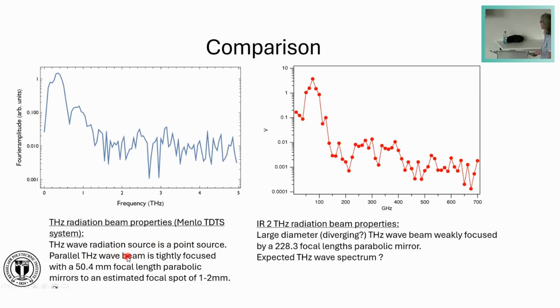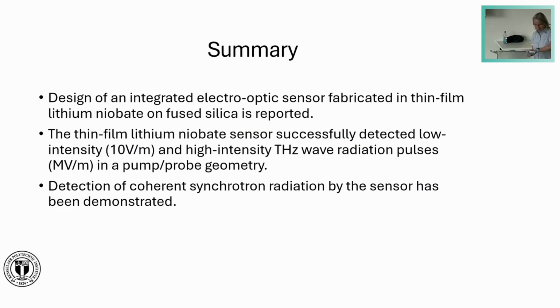We have a parallel terahertz beam, which is then focused in the end by a mirror with a short focal length onto a rather small spot. Whereas at the synchrotron beamline, the diameter of the beam is larger. It is likely also a kind of diverging beam which falls onto this parabolic mirror, which then produces a kind of weak focus where the detector is put. And as I said, I'm not an expert on the terahertz waves produced by the bunches, so I do not know what the expected spectrum is. But they look different.